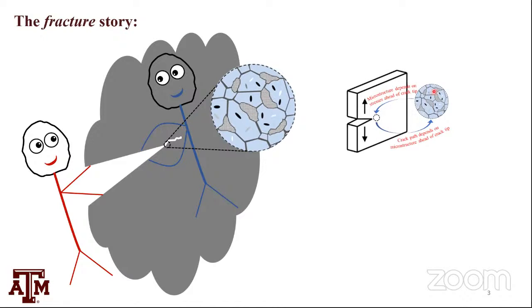Largely because once you have a crack tip and a microstructure, the driving force, the stresses that form once you apply, say, a mode 1 small scale yielding loading condition, give you a stress field or strain field that develops ahead of the crack tip and affects the microstructure. The microstructure evolution in this case means evolution of damage, or you may have phase transformation and things like that. And this evolution of microstructure affects the crack path. So it's a coupled cycle. Which one is affected more will depend on whether we get more resistance or it becomes easier for the crack to grow.